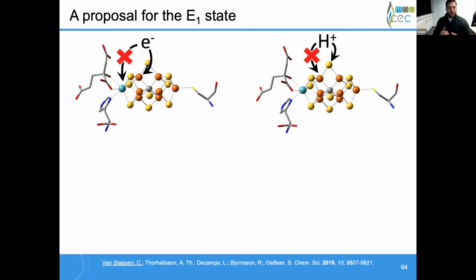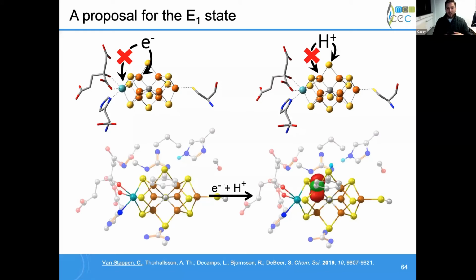And so from all of this together, we have a really precise proposal for what the E1 state looks like. So we do not have molybdenum-centered reduction, we have an iron-centered reduction. We have protonation of a belt sulfide, not another sulfide on the cubane or of the central carbide, for example, or formation of a hard hydride. And we have a very good idea of where reduction is actually occurring, that it's most likely on this molybdenum subcubane that neighbors the protonated sulfide.